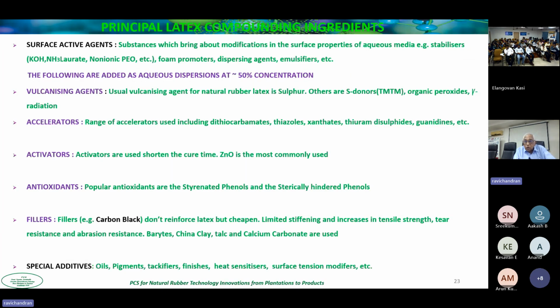Now, this is just a list of the various ingredients that we use in pre-vulcanization: surface active agents, vulcanizing agents, accelerators. These are all very fast curing accelerators, but unlike natural rubber, we have no scorch. We can add the fastest of accelerator, but the latex is still scorch free. Then activators, antioxidants, the styrenated phenols, and we want non-staining antioxidants because most latex products are light colored. So we don't want staining antioxidants which are used in dry rubber. And fillers, again, we don't use much filler in latex.